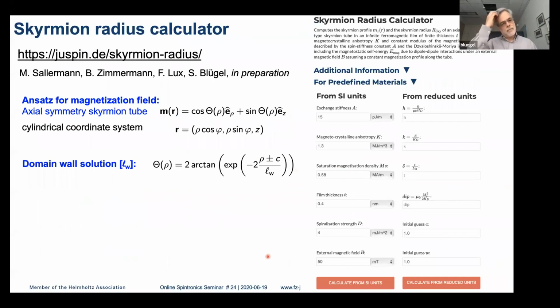And we have set up a Skyrmion radius calculator for the community, basically. So you can put in the numbers which you like to have, push a button, and then you get the Skyrmion radius. In this talk, I use the shooting method because we want to have a very fast web upload. Therefore, we used here the domain wall profile. It has some other advantages, which I may come to later.